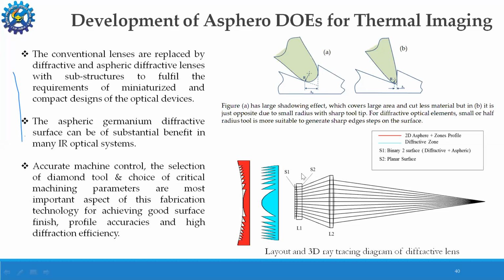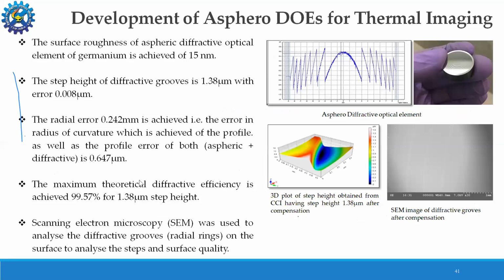So the challenge associated with this is the accurate machine control, proper selection of the diamond tool, and the choice of critical machining parameters, not only to achieve a good surface quality but also a very high diffraction efficiency. So we developed this germanium aspero-diffractive optical element, which was to be used for a thermal camera. This was a project funded by DRDO. So we could achieve a surface roughness of 15 nanometer.